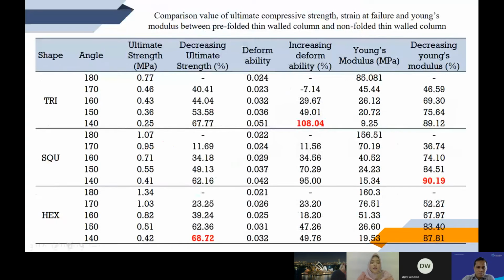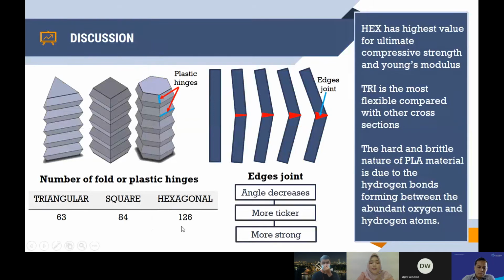And then this is the data for comparison of the values of ultimate compressive strength, strain at failure or deformability, and Young's modulus. In this figure, we know that introducing the folding pattern into a thin-walled column can increase deformability by 108.04%, decrease the strength by 68.72%, and decrease Young's modulus by 90.19%. There are two possible reasons why the folding angle and cross-section shapes can affect the compression properties and behavior.